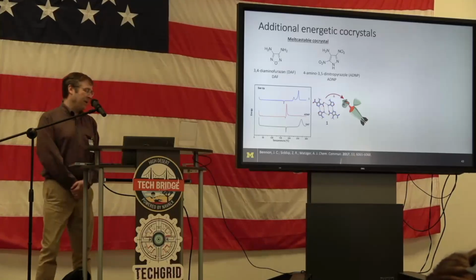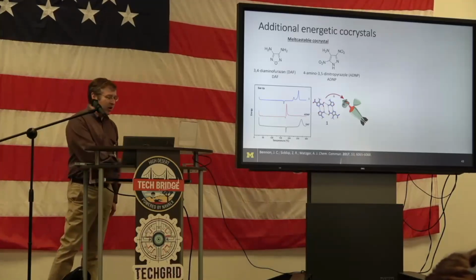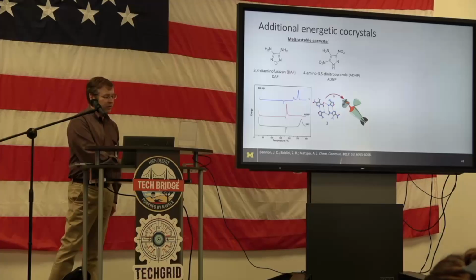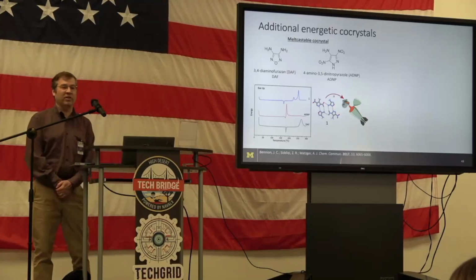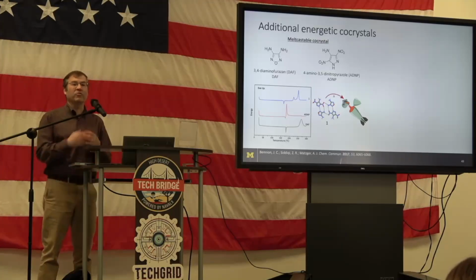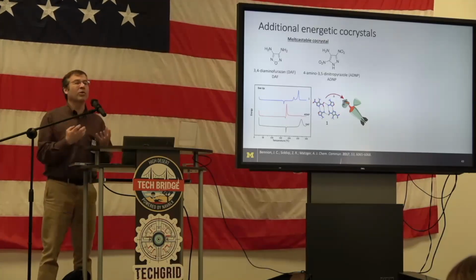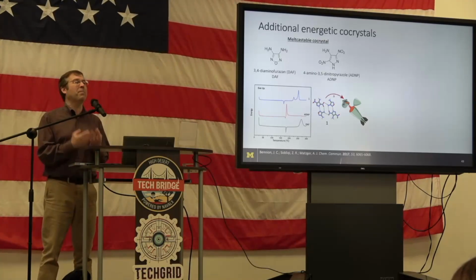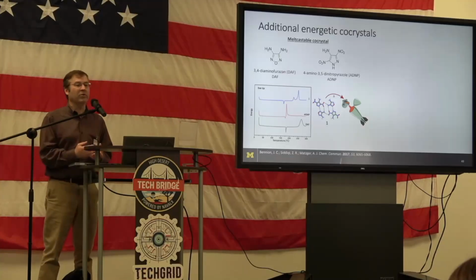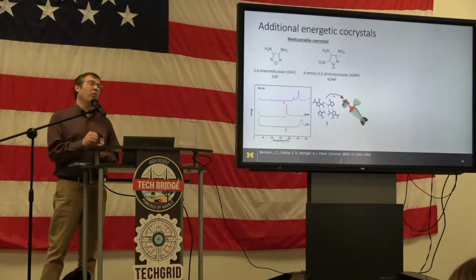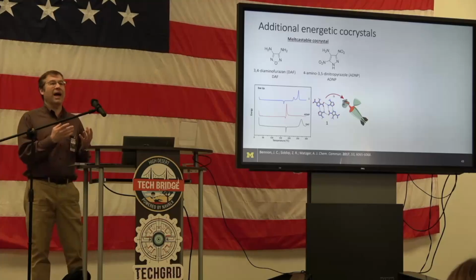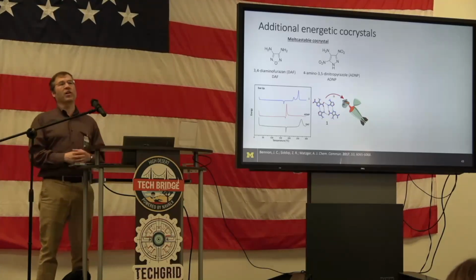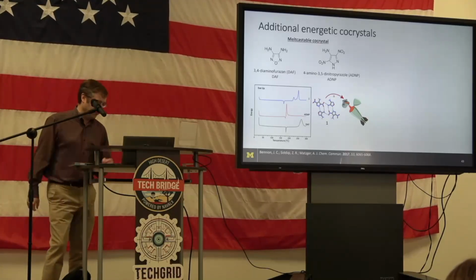And what's happening is in the melt of the co-crystal, shown here, you're actually suppressing the decomposition of ADNP, because the solution state, what's coordinating to that ADNP, matters in its stability. So that gives you enough of a window that you can actually have that stuff in the melt, recrystallize it, and get back the co-crystal.